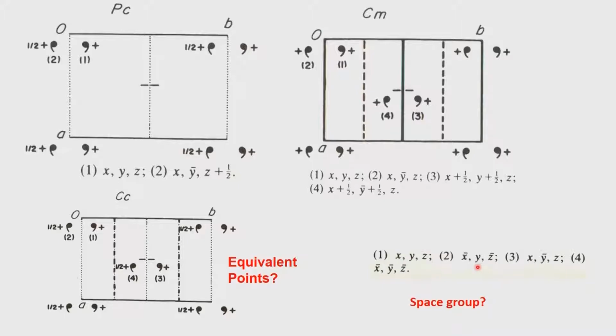So, that means that the centering is not seen. Generally, since the monoclinic symmetry is C centered, you should have equivalent points half plus x, half plus y, and since that is not appearing, this is a primitive lattice. So, the first conclusion is to examine the equivalent points, find out if there are any half translations associated with x or y, or in this particular example of a monoclinic symmetry, and then you conclude that it is a primitive lattice. So, we have found that it is a primitive lattice, it has a two-fold symmetry.